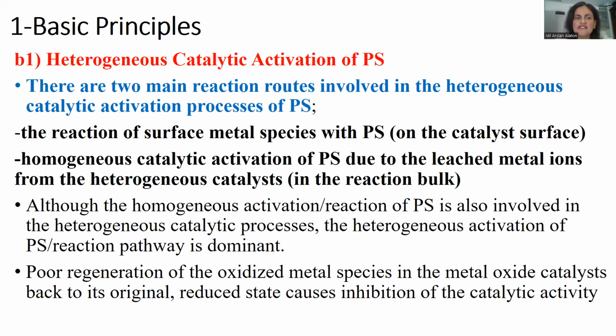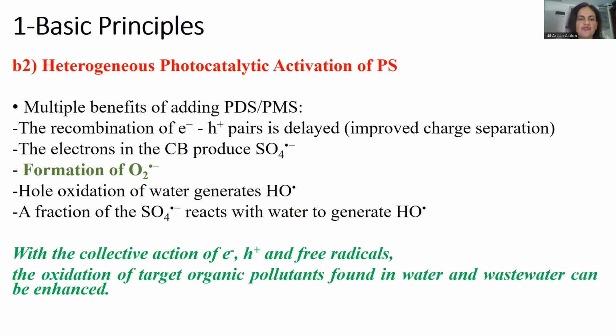Therefore, in heterogeneous catalytic activation, we have some advantages, like we can recover and reuse the catalyst. So there are, of course, also homogeneous reactions involved, not just heterogeneous ones. We have activation of the persulfate with the metal catalyst on the catalyst surface. We can have metal ion leaching, so that in the bulk, some Fenton-like reactions occur. But since this is a heterogeneous reaction, it is mainly occurring at the surface of the catalyst. The heterogeneous activation is dominating over the homogeneous ones. But again, here the concern is poor regeneration of the oxidized metal species and metal oxide catalysts to their original reduced state, which can cause inhibition of the catalytic activity.